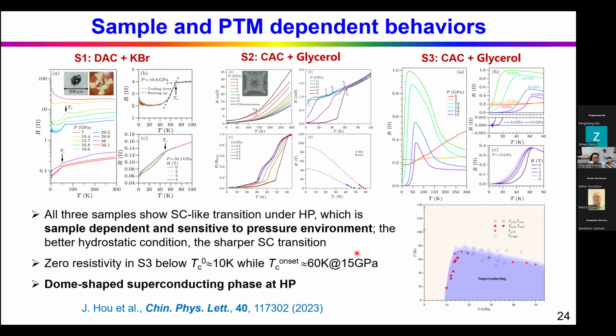Actually, my group has participated in the high pressure studies on the 327 phase in collaboration with Wang's group. So we are probably among the first few groups that became aware of the sample dependent behaviors in these 327 crystals. We measured 3 samples from Wang's group with different high pressure techniques, including diamond cell and cubic cell. And we also tried the solid pressure medium and liquid pressure medium. Every time we can observe some resistivity drop, but the behavior changed from sample to sample, and it's also very sensitive to the pressure medium. Only in the liquid pressure medium can we observe a sharp transition, and in one sample we can achieve zero resistivity, but it's quite broad.